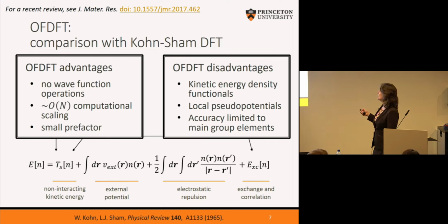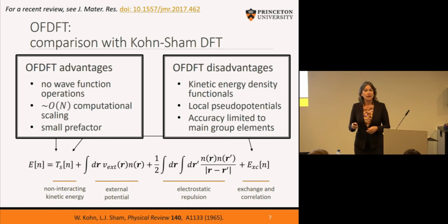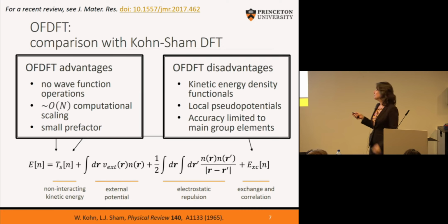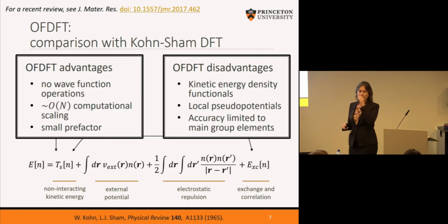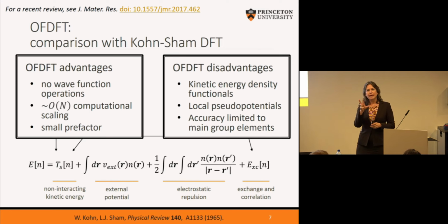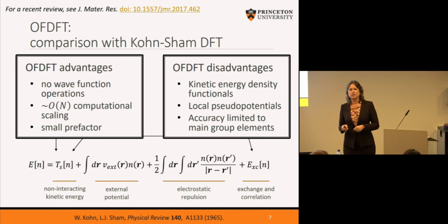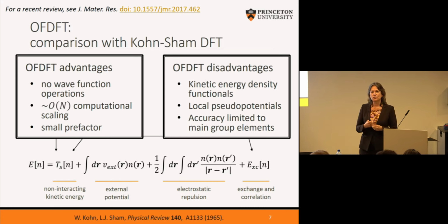We also have to use so-called local pseudopotentials, because non-local pseudopotentials usually require projections onto orbitals, and we don't have them. So that leads to some rigidity in the description of the interaction between electrons and the screened ion, the nucleus plus the core electrons. As a result, the accuracy has been mostly limited to main group elements. We did publish a couple of papers showing that you could, through some parameterization, introduce some angular momentum dependence such that you could treat transition metals. We did some proof of principle calculations for titanium. It's been a hard slog to get it to go further than that. That was a few years ago. It's a very hard problem.